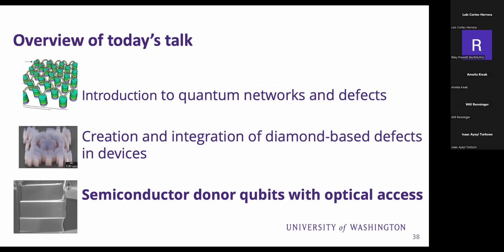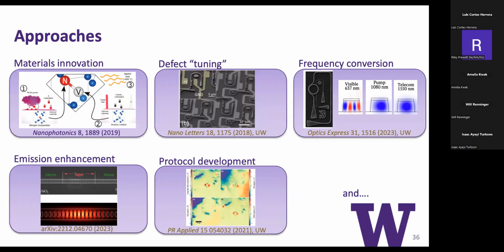Great. So what's the implantation energy of the nitrogen ions, and what's a typical annealing temperature? Yeah, so it depends on what we are trying to achieve. For getting defects that are 10 nanometers from the surface, a typical ion implantation energy is about 10 keV. For the work that we did with those inverse design photonics, I think the implantation energy was like 85 keV. We were closer to 100 nanometers from the surface in that case.